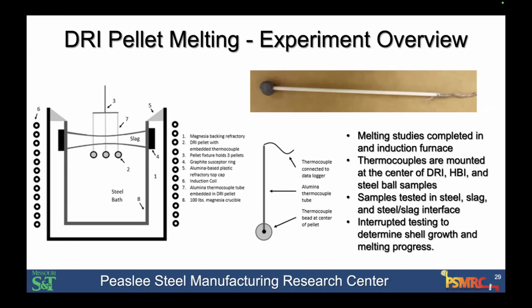The other thing that we've looked at is the physical experimentation of the melting behavior. As I mentioned before, DRI, when it's produced by natural gas, actually contains carbon, and oftentimes will contain upwards of 2.5% carbon. And that carbon actually has benefits in the melting behavior of DRI because the carbon in the pellet will react with the unmetallized portion of the oxides to liberate carbon monoxide gas. That carbon monoxide gas actually serves to agitate the bath and enhance the melting behavior. And we've done experiments in the lab to show this.